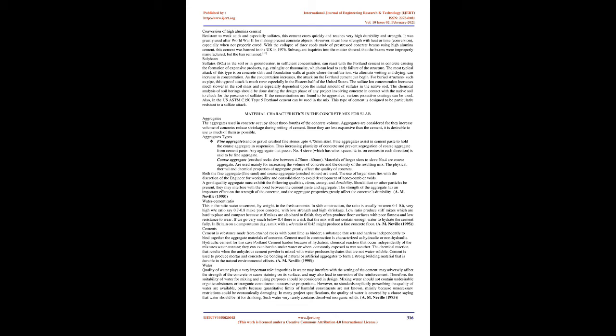Common failure modes of steel reinforced concrete. Reinforced concrete can fail due to inadequate strength, leading to mechanical failure, or due to a reduction in its durability. Corrosion and freeze/thaw cycles may damage poorly designed or constructed reinforced concrete. When rebar corrodes, the oxidation products, rust, expand and tend to flake, cracking the concrete and unbonding the rebar from the concrete. Typical mechanisms leading to durability problems are discussed below.